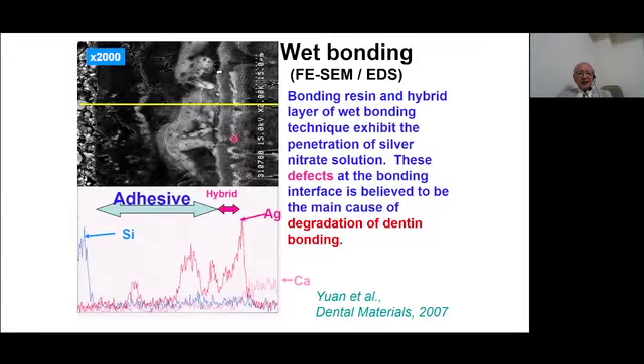Even in the dentin, the bottom of the hybrid layer, you can see the high peak of silver, and also in the hybrid layer you can see the silver penetration. Also in the bonding resin you can see the silver penetration. This is the defect at the interface. This is believed to be the main cause of the degradation of the dentin bonding.